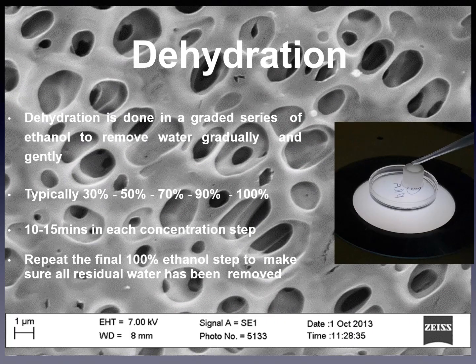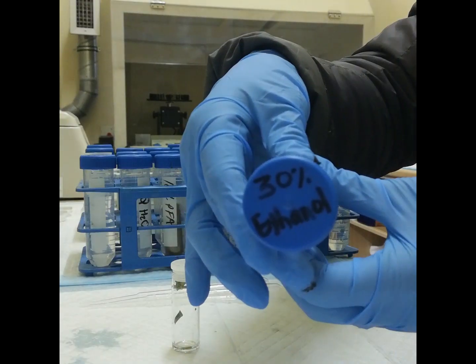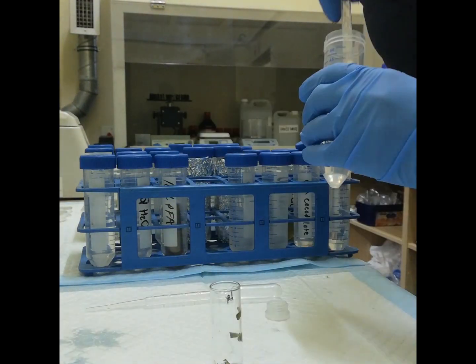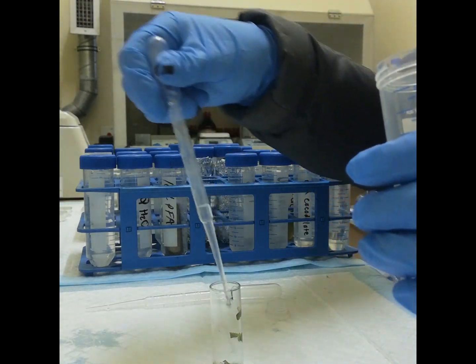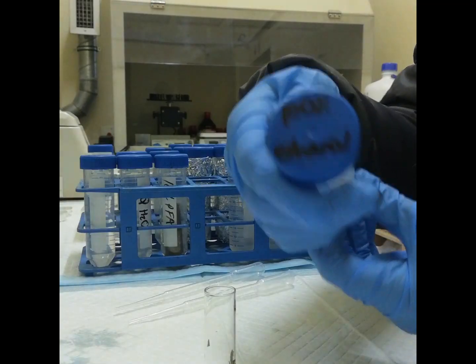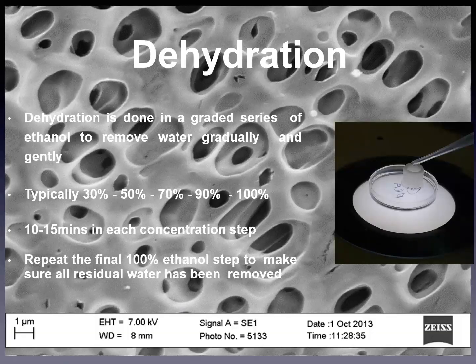Dehydration step. Dehydration is done in a graded series of ethanol to remove water gradually and gently, typically with percentages starting from 30%, 50, 70, 90, 100%, with 10 to 15 minutes in each concentration step. Repeat the final 100% ethanol step to make sure that all residual water has been removed.